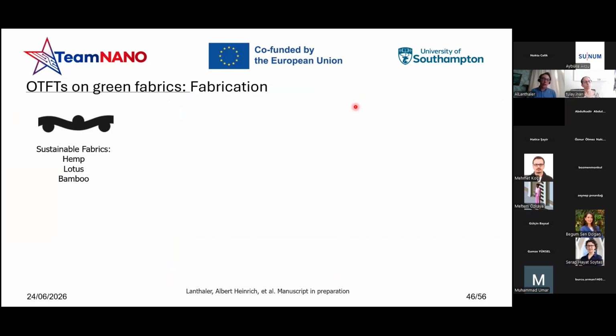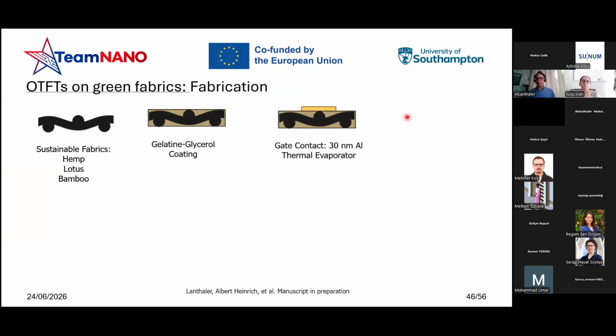So starting from sustainable fabric made out of hemp, lotus, bamboo, again provided by the Maiko company in Italy, in collaboration with the Max Planck Institute in Stuttgart, we decided to apply the same gelatin glycerol coating technique as mentioned before for the natural-based fabric, and to thermally evaporate 30 nanometers of aluminum on top of it. After that, in order to achieve a dielectric layer, this dielectric layer is composed of two parts.